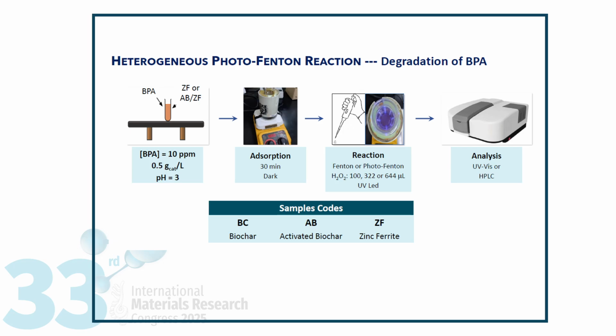Heterogeneous Photo-Fenton reaction, degradation of BPA. In a typical BPA degradation, the contaminant solution was mixed with the corresponding sample, and the suspension was stirred in the dark for 30 minutes to reach adsorption-desorption equilibrium. Subsequently, hydrogen peroxide was added, and the UV LED lamp was immediately turned on. Finally, the obtained samples were analyzed using UV spectroscopy and high-performance liquid chromatography. Remember, the codes of the samples are BC biochar, AB activated biochar, and ZF zinc ferrite.